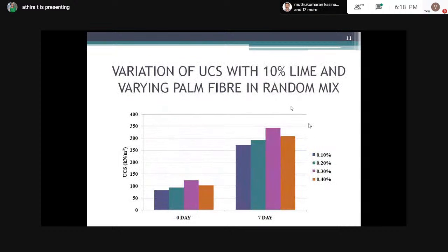Now with these OMC, we are conducting unconfined compression test for different percentages of fiber. In first case, we are mixing the fiber randomly with the soil lime mix, and we are conducting the UCS test. We can see that up to 0.3% it showed an increase, and after 0.3% it shows a decrease in the strength. By comparing the results for 0-day and 7-day curing, we see that the 7-day cured sample shows an improvement much higher compared to the 0-day cured sample.